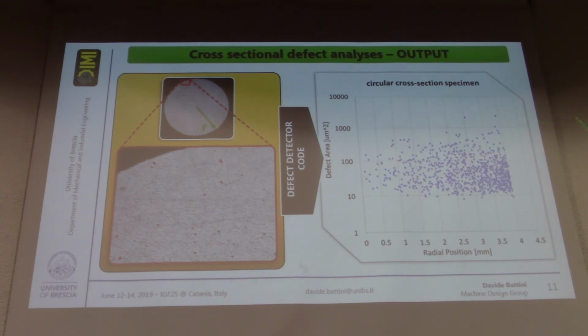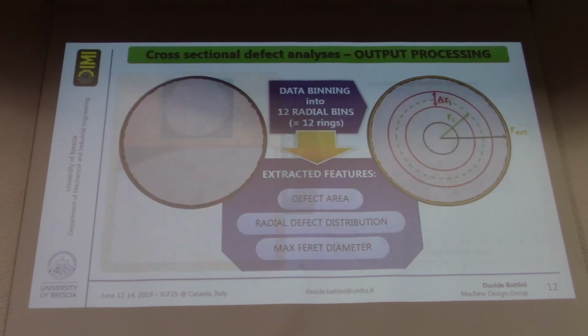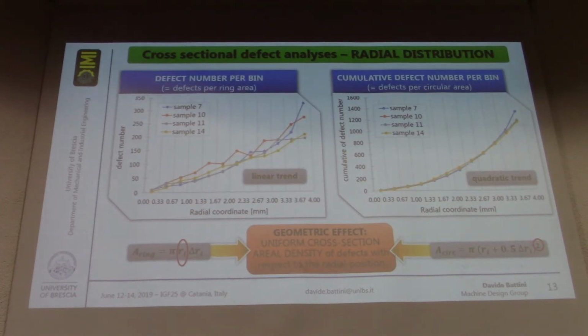But since these data are way too much, we decided to process the data by applying a data binning technique, and we divided our cross-section domain into 12 radial bins, which basically are simply 12 concentric rings with the same thickness, right? And we just extracted a few features like defect area, radial defect distribution, and the maximum Feret diameter.